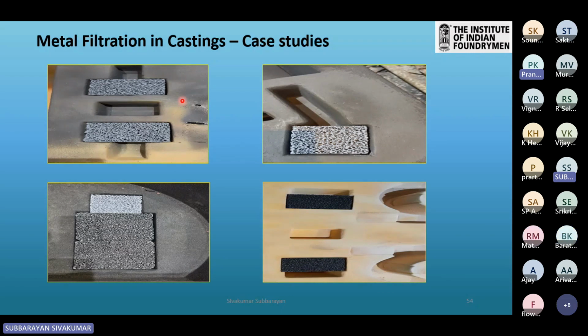The purpose of placing the filter is to filter out the unwanted things. When we create such gaps, the unwanted non-metallic inclusions float through these and enter the casting. Of course, 90% or 80% will be filtered out, but we do not know where that non-metallic inclusion will sit in the casting. If it comes in the machining area, then the entire effort is gone. Similarly here, a huge gap. Here we have multiple sizes of filter, and again this gap is a typical killer in the foundry.